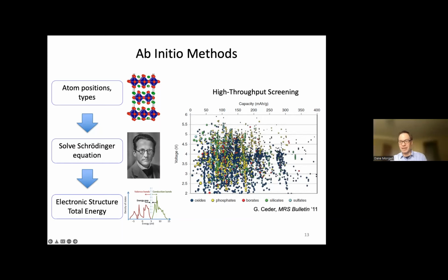And here's a representative example from a while back from the Ceder group, who's done a lot of work in this space in batteries, in fact, where they screened a lot of potential cathode materials, looking at their ability to hold lithium, which was their capacity, and looking at their electrochemical potential for lithium, which gave you the voltage. And those are essentially just a handful of energy calculations that you can do with quantum mechanical methods. And they were able to screen hundreds, even thousands of materials and look at typical potential capacities and potential voltages.